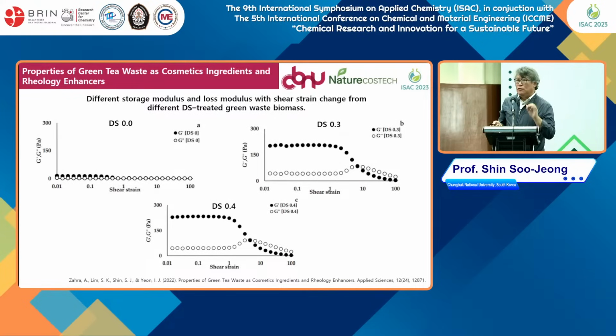We also measured gel strength via storage modulus and loss modulus. Without chemical pretreatment, we get not a gel-like material, just a watery material. With carboxymethyl pretreatment, we can get gel strength, and with carboxymethylation at DS.3 and DS.4, we get strong gel properties.